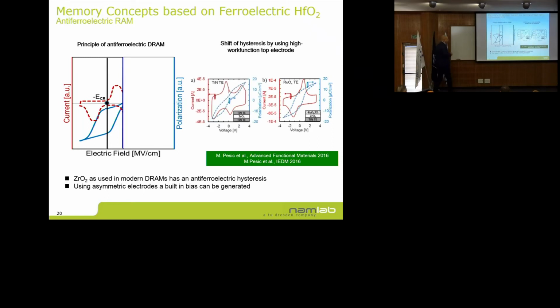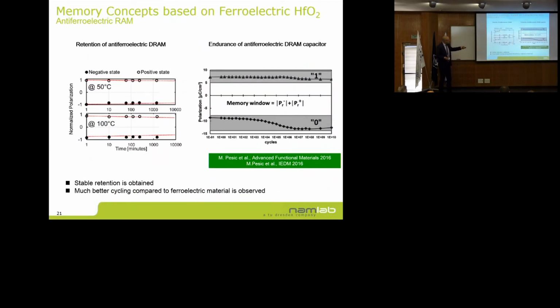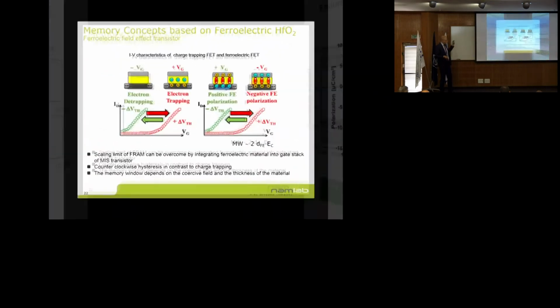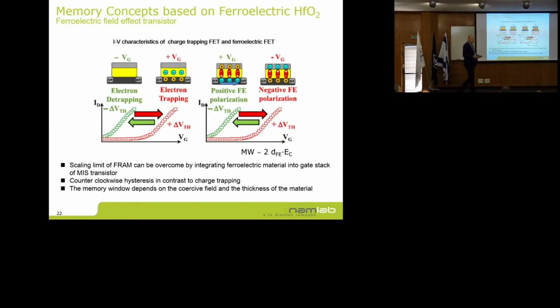And we did that by changing one of the electrodes to a high work function electrode. And indeed, then we can shift the polarization curve, and we only have one polarization loop that looks like a ferroelectric again. And with this trick, immediately we get much better cycling, which we have now pushed already to 10^12 and beyond cycles in this type of concept. And it's also stable with respect to retention. Now, another way of doing a non-volatile memory out of the ferroelectric is to integrate it into a transistor.